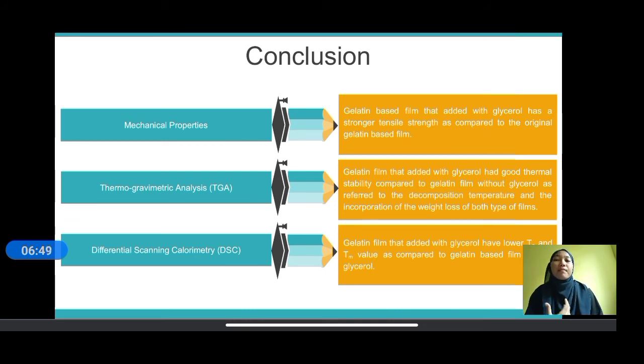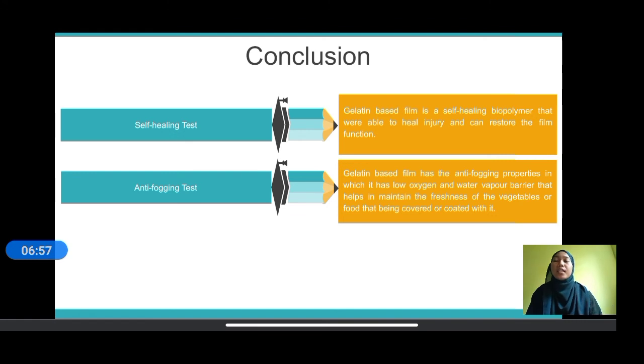And then the gelatin film added with glycerol has lower Tg and Tm values as compared to the gelatin-based film not added with glycerol. We can also conclude that gelatin-based film is a self-healing biopolymer that is able to heal injury and restore the film function. Gelatin-based film has anti-fogging properties, with low oxygen and water vapor barrier that helps in maintaining the freshness of the vegetables or food covered or coated with it.